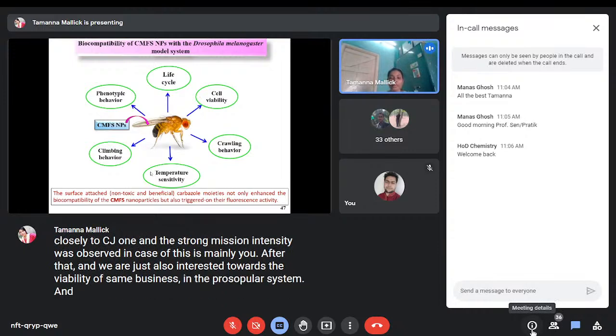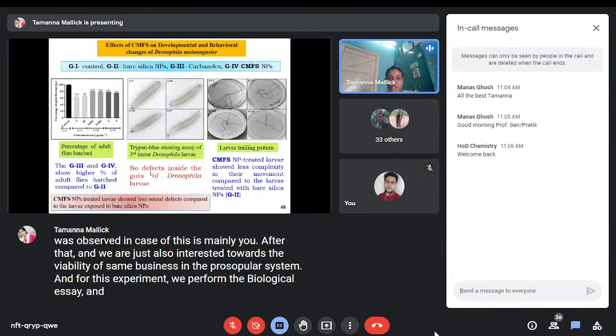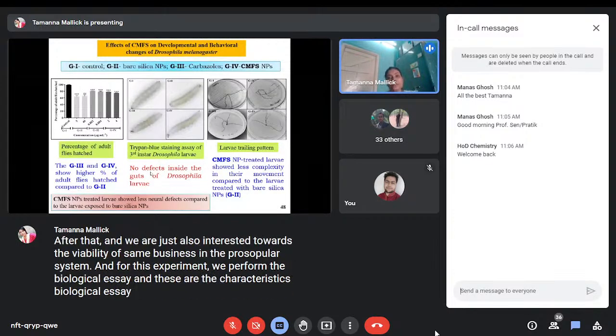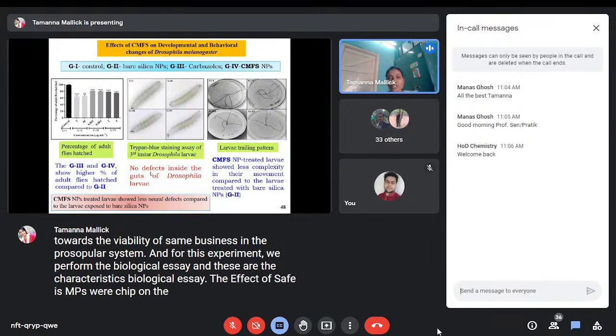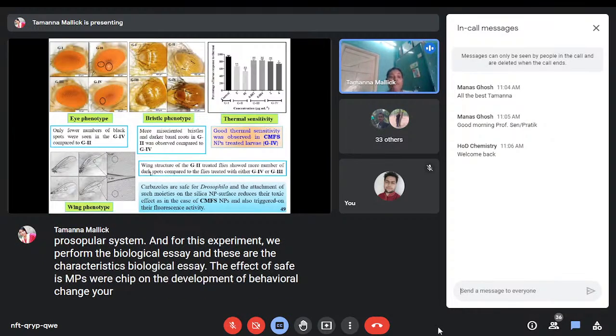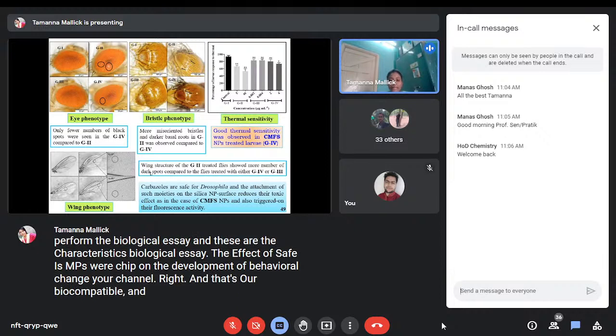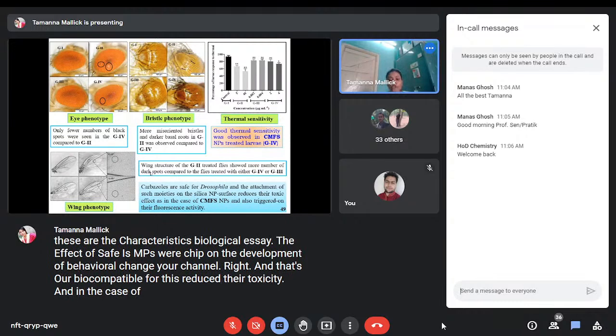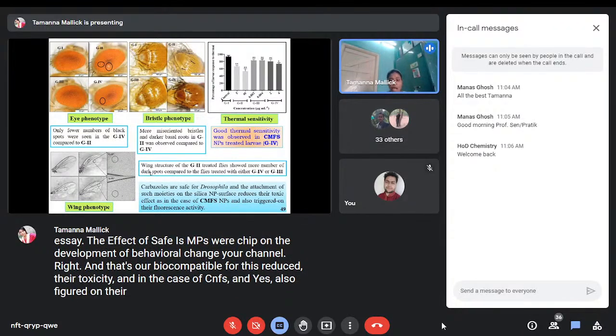After that, we were also interested in the biocompatibility of CMFS NPs in the Drosophila melanogaster model system, and for this experiment, we performed the biological assay. And these are the characteristic biological assays. The effect of CMFS NPs was checked on the development and behavioral change of Drosophila melanogaster, and the phenotypic behavior and thermal sensitivity were also checked. It is concluded that the carbazoles are safe for Drosophila, and the attachment of such biocompatible carbazole moiety on the silica nanoparticle surface reduces their toxicity, and in the case of CMFS NPs it also triggered their fluorescence activity.